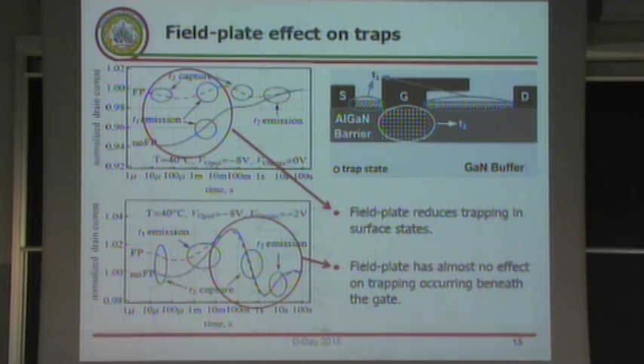As you can see here, the emission that we observe in the case of the field plate for the first trap, T1, is strongly reduced in the device with a field plate. On the other hand, the field plate does not have an effect on the traps located beneath the gate.